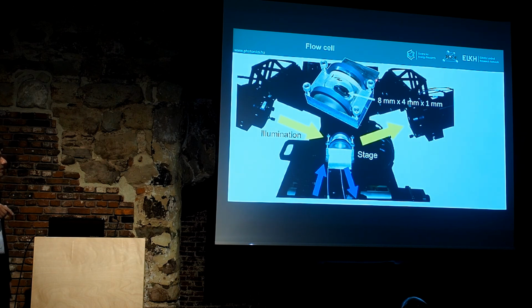And in this cell, we can measure how, for example, protein molecules adsorb at the surface. And we can measure it during the adsorption. It means that in one second resolution, we have this large amount of data, and we can create models, and we can fit the thickness, the refractive index, the volume fraction of proteins at the surface. So even just when several molecules start to accumulate at the surface, you can already measure very sensitively and non-destructively. So this is one example of what we can use it for.